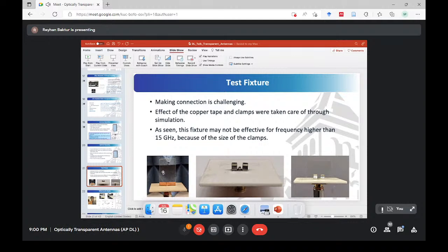Is the transparent material indium tin oxide or something else? This particular one we examined, and the one we have here is silver nanowire. Indium tin oxide is good. If you would like to use that, it's a great one to use. The only reason people are trying to explore silver nanowire, or treated or hybrid silver nanowire, is that, one, indium and tin are limited. I mean, of course, silver is limited too, right? Two, indium tin oxide is hard to print on flexible surfaces, like contact lenses or anything flexible. It has its challenges.